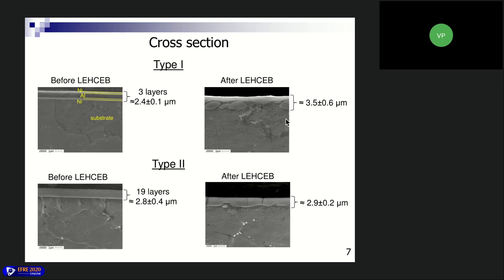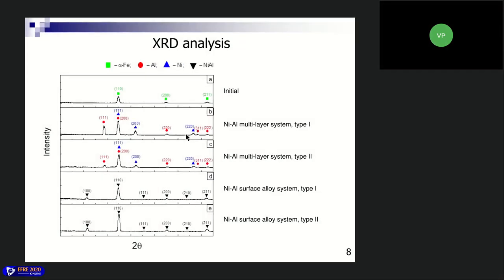In the case of thick layers, we can see the uniform border. There are some globules which are surrounded by the material of the substrate, and the thickness of this surface alloy is 3.5 micrometers.